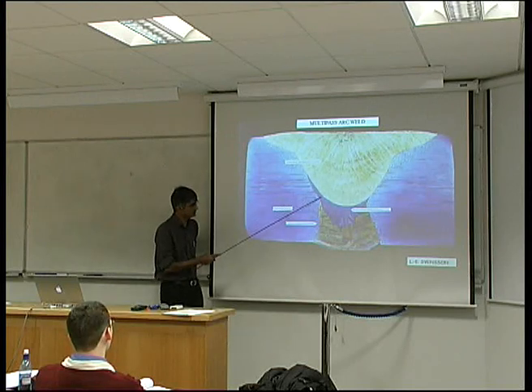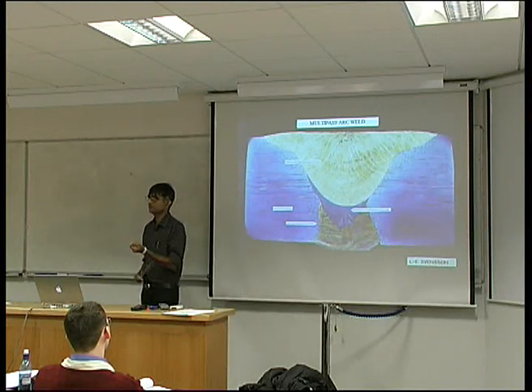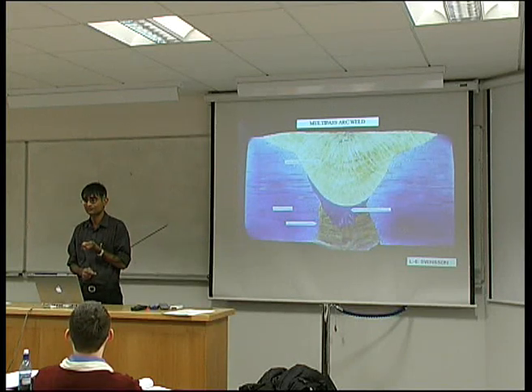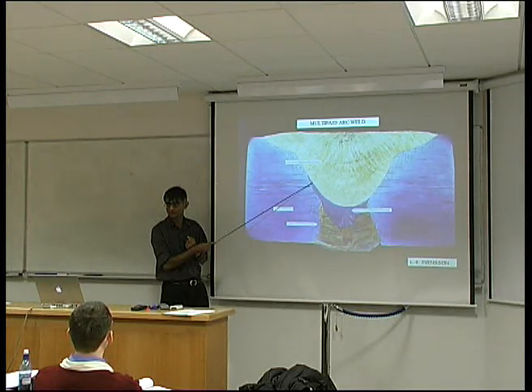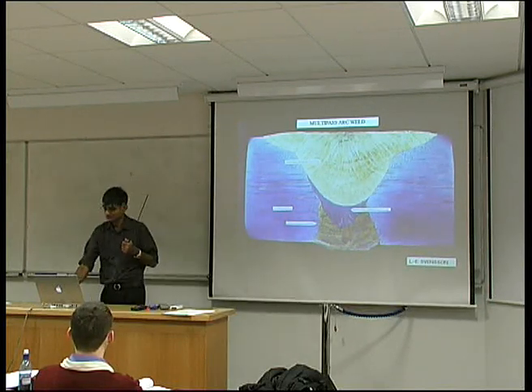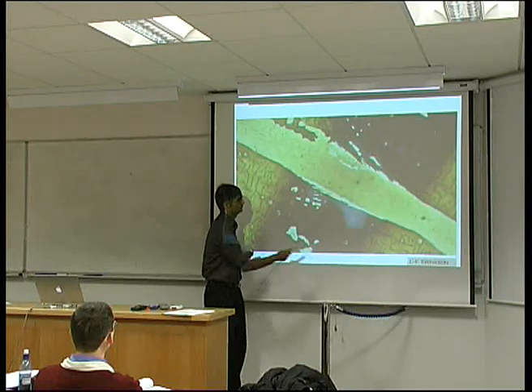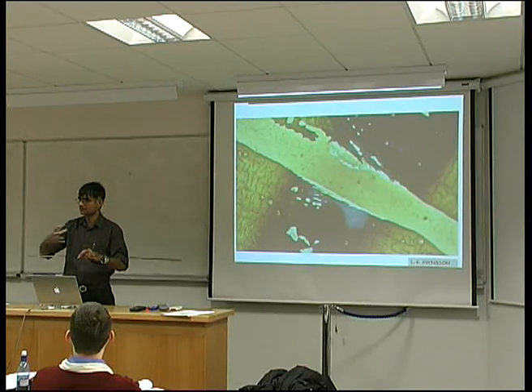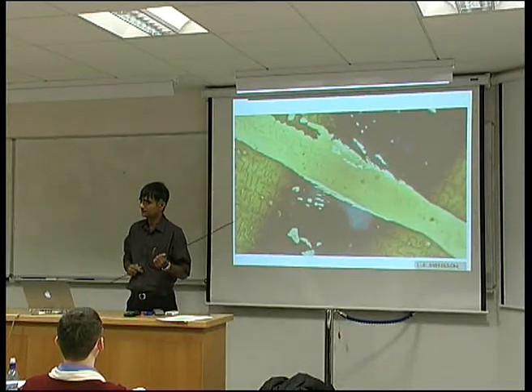I'll focus today on the fusion zone microstructure. The first thing you notice is these columnar grains — it's almost like the picture of an ingot, where you nucleate grains at the solid-liquid interface and they grow along the direction of maximum heat flow. This is a higher magnification image of those grains. They are of the order of 100 micrometers wide, have the shape of a hexagonal prism, and are approximately 5 to 10 millimeters in length.